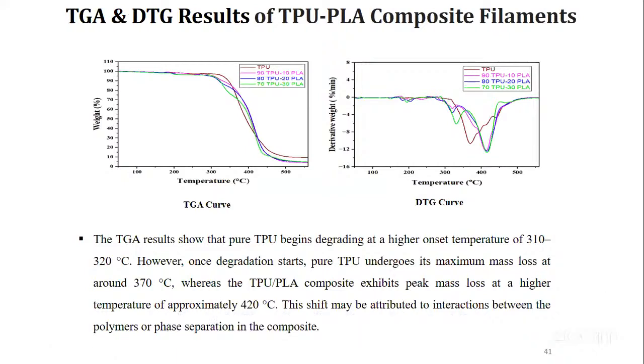Yeah, so then we took the filaments that we extruded after the single screw extrusion, and we tried to understand how temperature is degrading them through the TG and DTG results of these TPU PLA composite filaments. The mass loss was higher at approximately 420 degrees centigrade. TPU undergoes a maximum loss at 370, and TPU and PLA's loss is at 420 degrees centigrade.